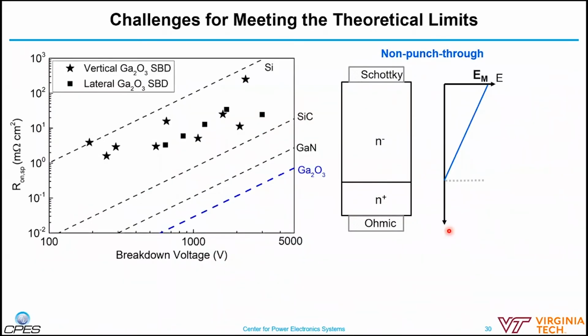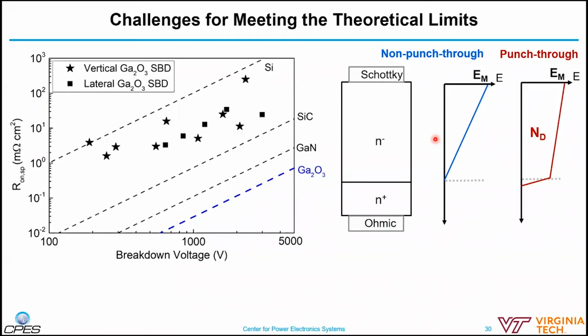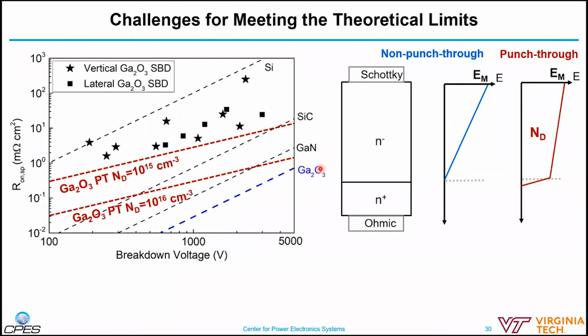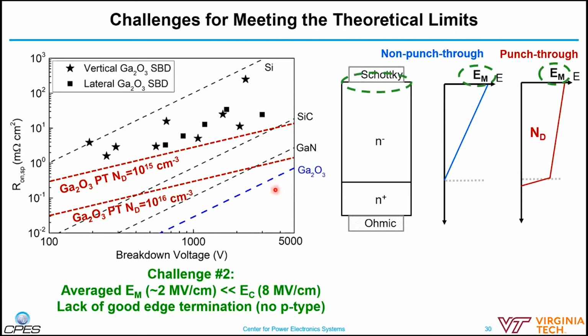Okay, so what are some of the challenges for meeting the theoretical limits of ultra-wide bandgap gallium oxide? Now I just provide some perspective from the device point of view. One of the challenges is the drift region design. Most gallium oxide devices, let's say vertical devices, are now based on a non-punch-through electric field design. If you look at the electric field distribution, it intentionally uses a very lowly doped drift region to maximize the breakdown voltage that people can get from this drift region thickness. But that's at the price of a higher on-resistance. If you look at the punch-through design, the limit is actually much inferior compared to a non-punch-through design.